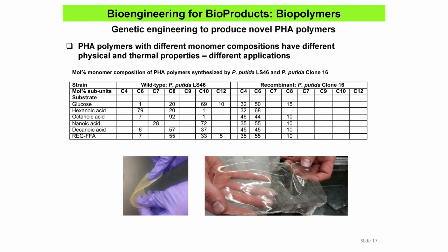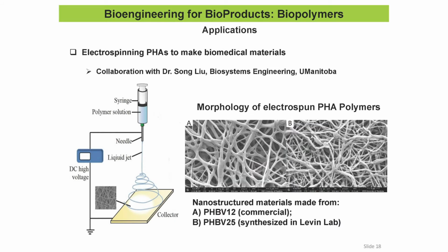Anyway, but what can we do with them? Well, in collaboration with Song Liu in Biosystems Engineering, we did this electrospinning. We took the PHAs that we could make in the lab. So we had a PHBV, or polyhydroxy butyrate valerate, with 25% valerate, 75% butyrate, or a commercial PHBV with 12% valerate and 88% butyrate. And he used this apparatus where the polymer is in a syringe and it's drawn to a surface using a high voltage differential, a DC voltage, and creates these nanofibers. Okay? So this is made from the commercial PHA. This is made from our PHA in the lab.